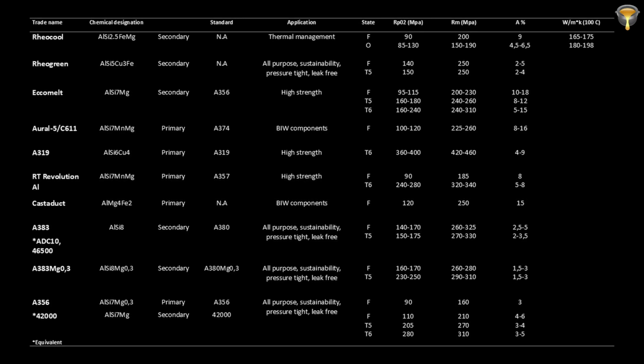And we will also show a graph where we have different alloys from 2.5% silicon to 7-8% silicon in a range where you have different properties for these castings. And that is best when you see it on the screen when you're watching the video. We don't go into every alloy in that audio feed. But the key thing, and that is also a big advantage in Rheocasting, is that the castability isn't defined by your silicon content, as when you see it in high pressure die casting.